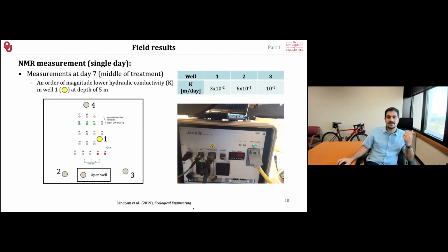After 7 days, we were able to see that the signal in the well, in the middle of the treatment area, right between this red and green, has an almost 1 order of magnitude less hydraulic conductivity measured from NMR compared to these wells outside of the treatment area. That means that a lot of water has been pushed out and been replaced by solid particles of calcite. This is great. This is showing us, okay, something is happening.